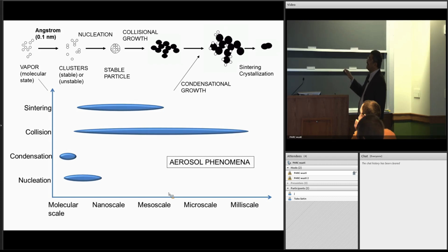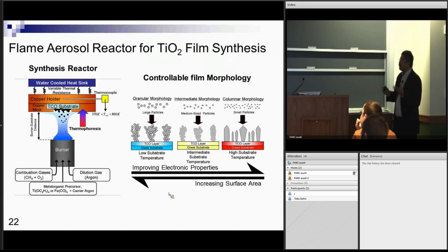Two particles could collide, and you can see that I have an agglomerated structure. Now I'm dealing with particle-particle collisions, so it could take place over all these different scales. This could be a time scale, this could be a length scale, you can choose. And then once I have a structure like this, it might collapse back. It's in a high temperature environment, so the preferred shape is a sphere, and it might collapse back into a spherical structure. And this condensational growth was shown here. So the size changes, the composition can change, all kinds of things can change. The crystallinity can change. So we want to understand this to control our growth processes.